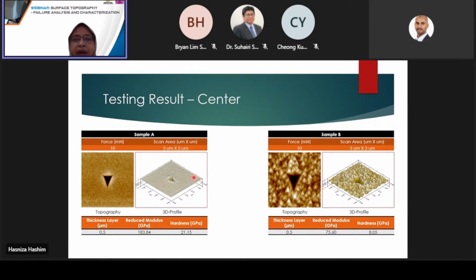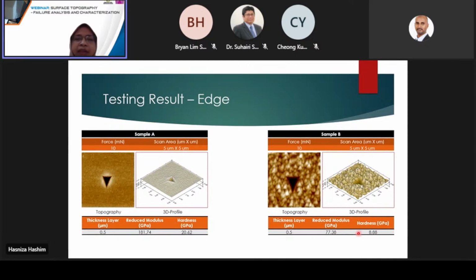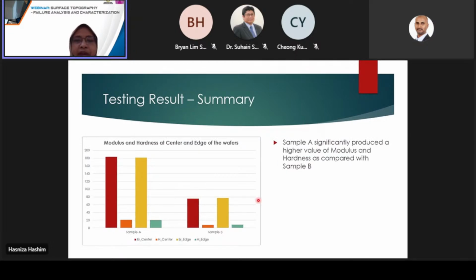So this is the result at the center of the wafers. Sample A produced a modulus of 180.84 gigapascal, and the hardness is around 21.15 gigapascal. For sample B, the modulus is 75.6 gigapascal and the hardness is 8.05 gigapascal. The same goes for the result at the edge of the wafer. When we plotted the histogram, we can see that the hardness and modulus of sample A at the center and edge is higher compared with the hardness and modulus of sample B, even though the thickness of the layer is the same, which is 0.5 microns. We applied the same force to both samples.